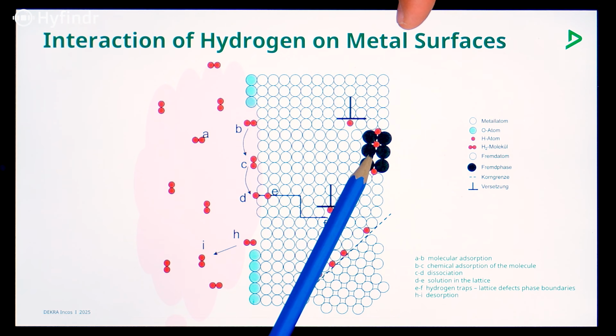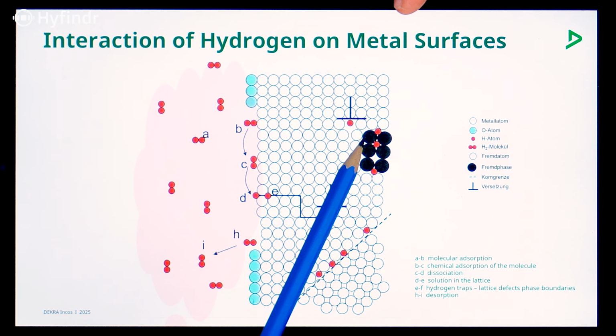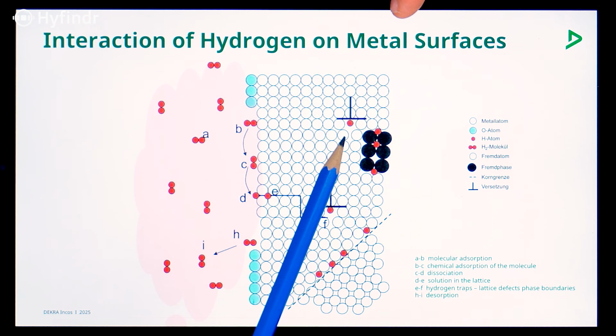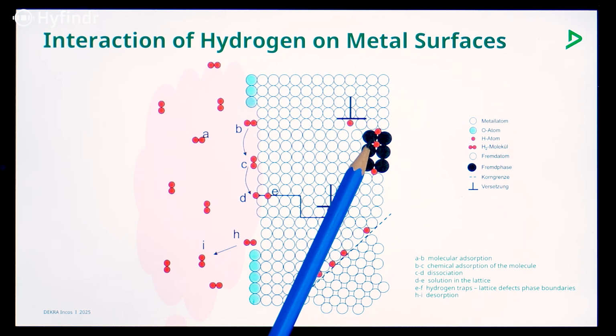Very, very simple. I just want to go back just one video because this is so important. So show us embrittlement here. Can we see that on this? No, the embrittlement is here when we are coming back to the molecules. Then we have the embrittlement. Each molecule of hydrogen in the lattice will decrease the plasticity. And because a molecule means larger volume, we have internal stresses. So the hydrogen having gone into the material, now causing internal stresses, reducing the plasticity, that's embrittlement.